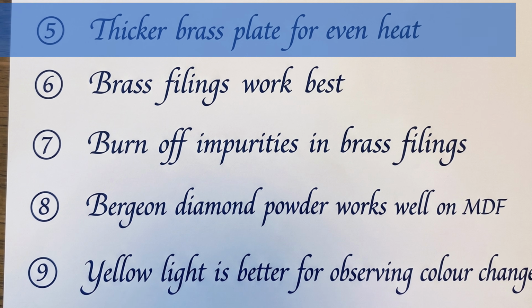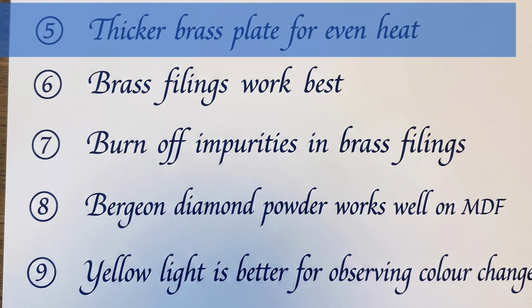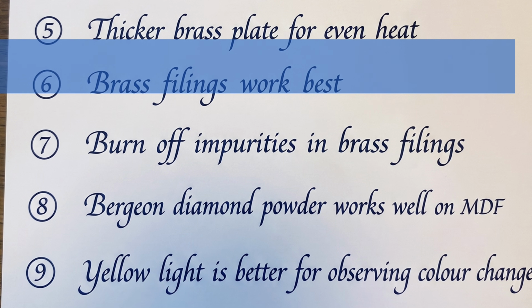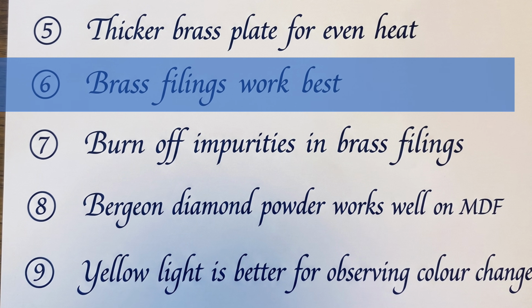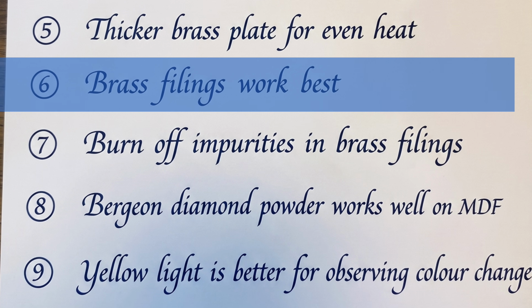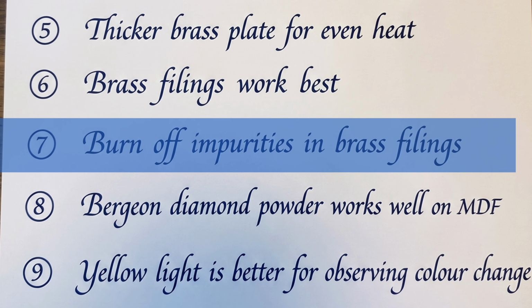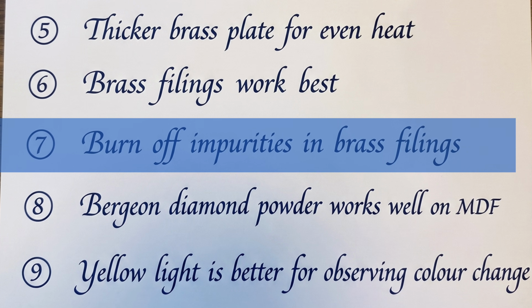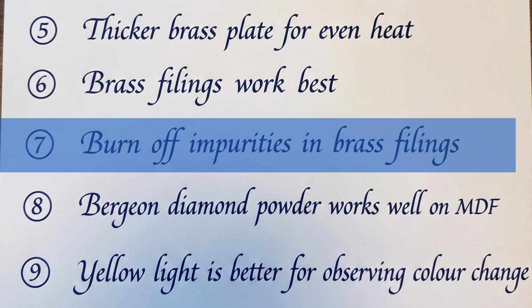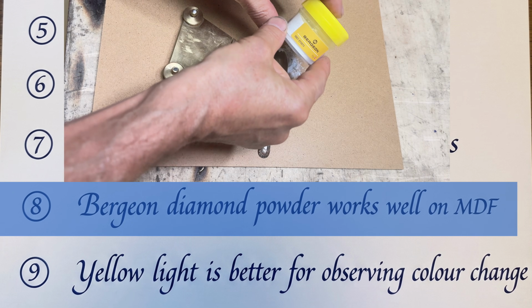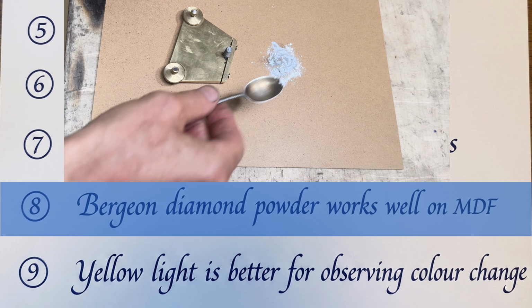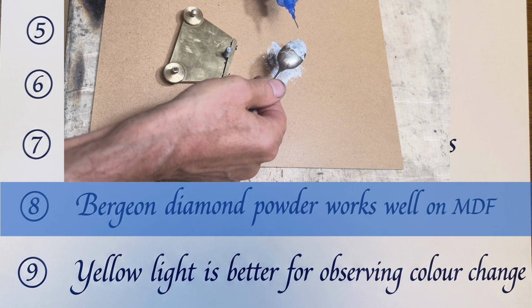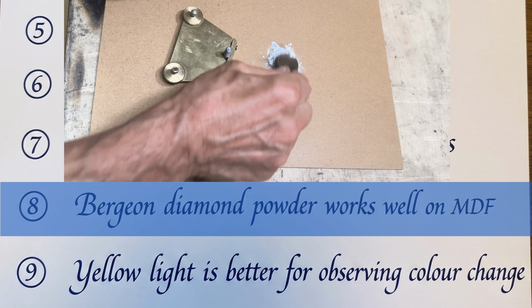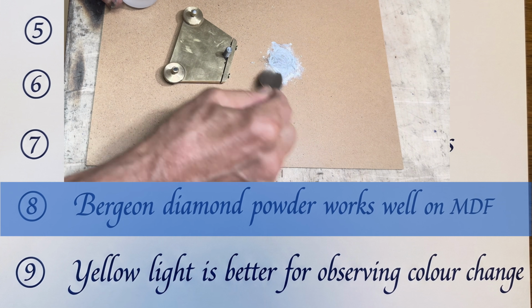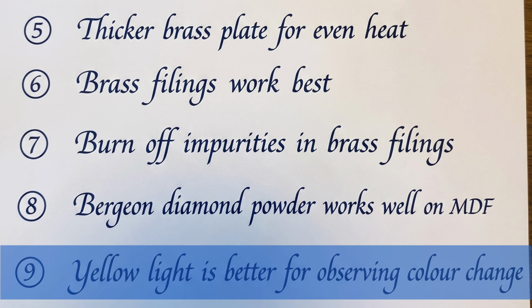When bluing, use a thicker piece of brass which will much more evenly distribute the heat for a better bluing. For me, brass filings worked better than the brass sheet. I felt I had more control over the bluing process. But if you're going to use brass filings, it's essential that you burn off all the impurities, because these may affect the bluing process. This extra fine Bergeon diamond powder produced an excellent result when mixed with alcohol and used on an MDF sheet.